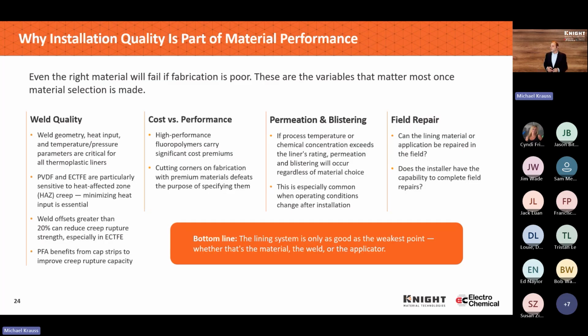But also weld locations. The design on the front end is really important. If you heard me mention in the beginning with the different testing, I recommended adding a weld sample to be tested, because the welds are typically the area where problems occur first. So location of those welds becomes really important. If you can put the welds into an area that sees less stress overall, then you can maximize your chance for success. So you've got weld quality and weld location that are important.